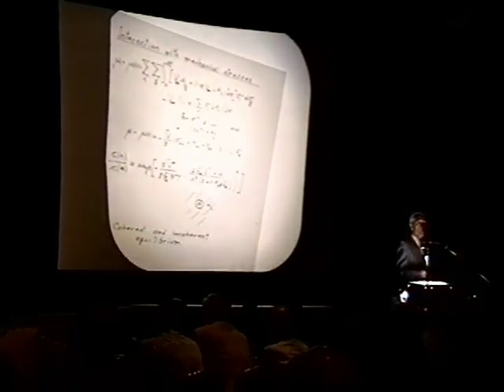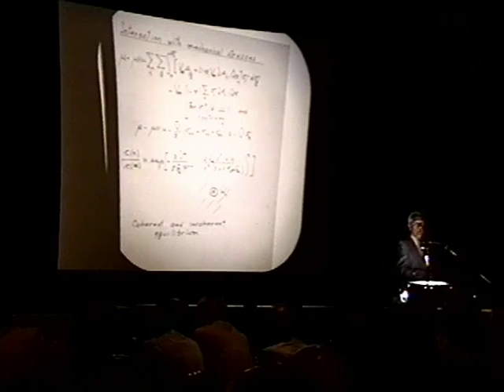This can be converted to give an expression for the excess concentration in a tensile stress field for constant chemical potential between the relaxed body and the stressed body. This is a perfectly general thing. This is a simplified version of this. And if you look at this carefully, you find that the shear stresses also play a role, a lesser role than the hydrostatic stress, but not zero. So that in the field of a screw dislocation, you will also have an enhancement.